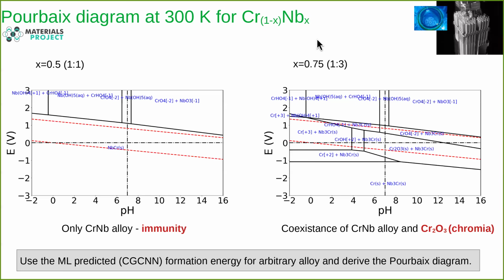If you further go to higher niobium content, then you will see again in this range where the chromia and the alloy will be coexisting. That suggests that with this concentration, if you deposit such a coating on a fuel rod, then you expect the standard oxide, the chromia plus the chromium niobium alloy. So it will be passivated in a way that an oxide will passivate the corrosion of the material. And then, of course, if you use our CGCNN model, which is inbuilt, you can actually calculate the Pourbaix diagram for an arbitrary alloy.